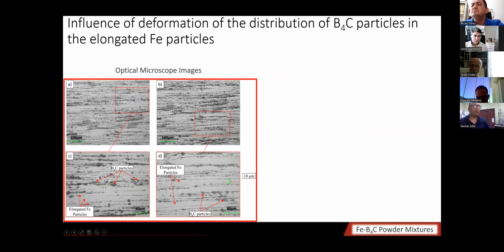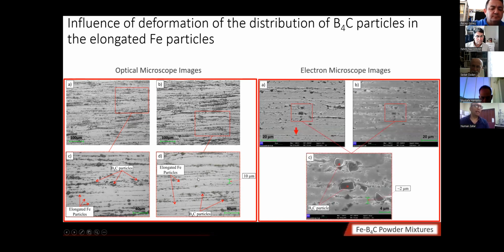Okay, this is the ultimate deformation level which I have been able to achieve after the cold rolling. These are my 1 millimeter wires, in which you see that all the agglomeration which occurred at N15 at the lower deformation levels has reduced at the higher deformation levels. They have been forced to be embedded in this direction like this. This condition is favorable for us because agglomeration is not desired. And the electron microscope images also reconfirmed that iron particles have not been agglomerated anymore thanks to the deformation level.